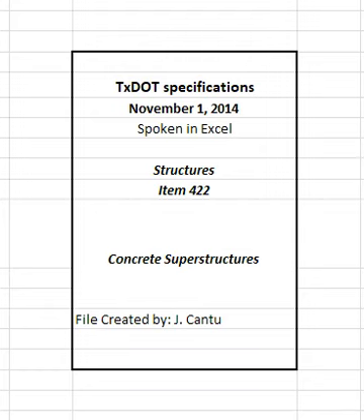4.10 Defective work. The contractor is responsible for the ride quality of the finished bridge slab. The engineer will use a 10 feet straight edge, 1/8 inch in 10 feet, to verify ride quality and determine locations where corrections are needed. Submit a plan for approval to produce a ride of acceptable quality if the engineer determines the ride quality is unacceptable. Make all corrections for ride before saw cutting grooves. Repair defective work as soon as possible. Remove and replace at the expense of the contractor any defect that cannot be repaired to the satisfaction of the engineer.